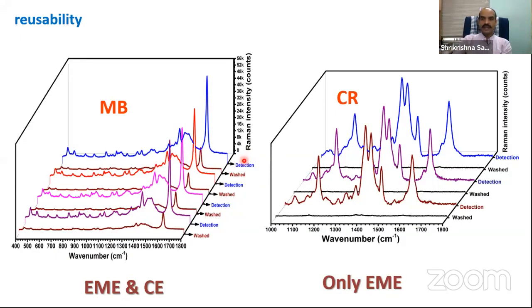Means if I detect this dye, can I reuse it again? For example, for this Congo Red, the dye is physisorbed, and therefore if I do this detection, this SERS, I can wash it. If I wash it, a simple wash with water, I can get zero intensity. Again, I put this dye, and I get intensity again.